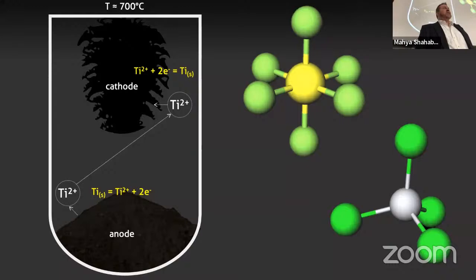We frankly started off, and I'll give the synopsis here, we started off looking in the wrong direction. We were looking at the Raman spectra that are coming out of that, because that's a very typical way to do a very good job on this. Deeply colored melts, the Raman spectra are very fine-tuned, but the excitation is easily lost. So you need to be really close. And with these deeply colored melts, we were losing the Raman signal out. So actually the simpler way, UV vis, turned out to be the much more appropriate way in a darkly colored melt in order to look at this composition change. So that's what we did.